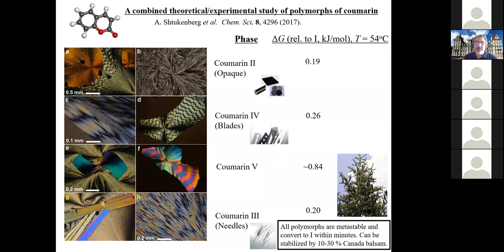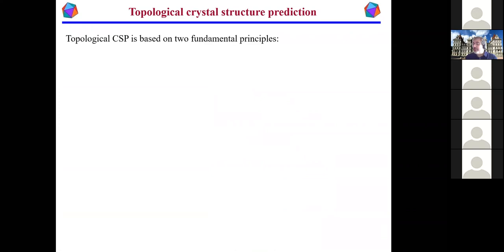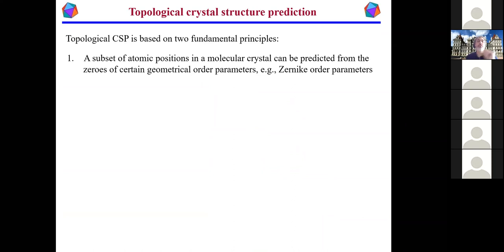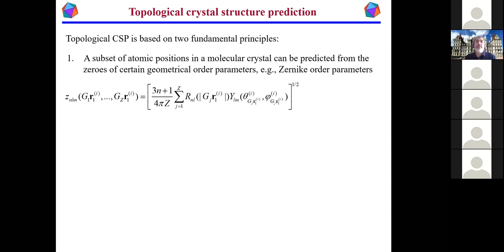Now, the idea of using geometry and topology to predict crystal structures is really based on a few fundamental principles. One is that these special positions that I was telling you about actually turn out to be minima that can be predicted using a set of geometric order parameters. For example, in this case, we picked the Zernike order parameters, which are often used in 3D image analysis. And they look like this, right? By the way, that 1/2 should be a 2, not a 1/2. If you know anything about Steinhardt order parameters, they look like that, except for the fact that they have a radial polynomial.